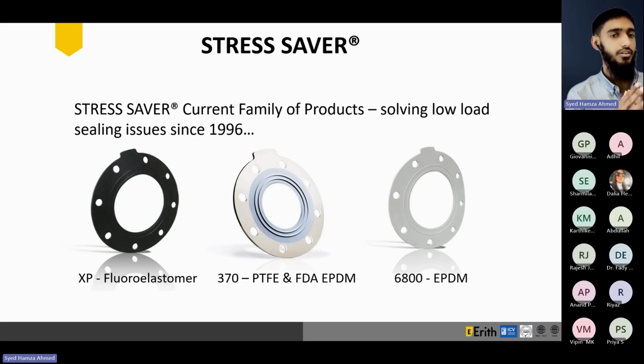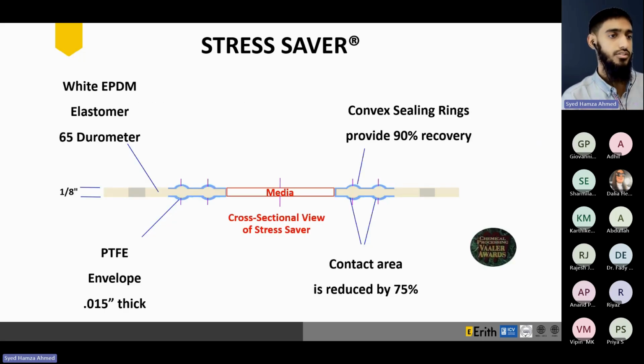The stress saver is a type of gasket that can solve low load sealing issues, and there are different models based on the material of construction. We have the fluoroelastomer models, we have the EPDM model, we have the PTFE model. Basically, how the stress saver works is that it has a molded in sealing ring that creates 75% less surface area for high performance in non-metallic flanges. Again, it has low seating stress due to the reduced area, and we can use the specialty PTFE gasket, and these can be used in both raised face as well as full face flanges. The contact area is reduced by 75%, as you can see in the diagram.